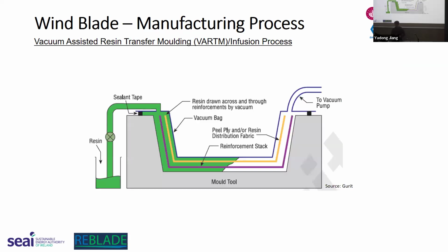So this is just a quick diagram that I got from Gurit, who supplied the epoxy resin. As you can see here, you have your resin pot, which contains your liquid resin. And then you have your mold tool. The purple line is your reinforcement stack, or your dry glass fiber or carbon fiber, whatever fiber reinforcement you want to use. The yellow line is your peel ply or resin distribution fabric. That's to encourage the resin to penetrate the fibers and flow across your material from one side of the mold to the other, to the vacuum pump at the outlet.